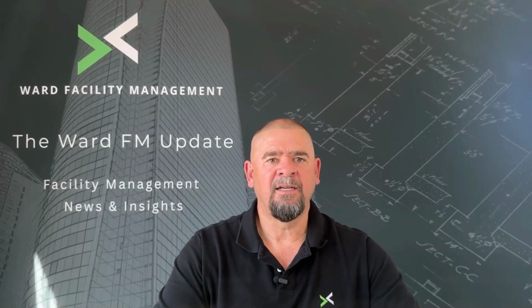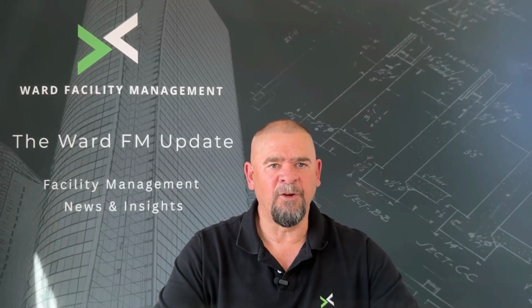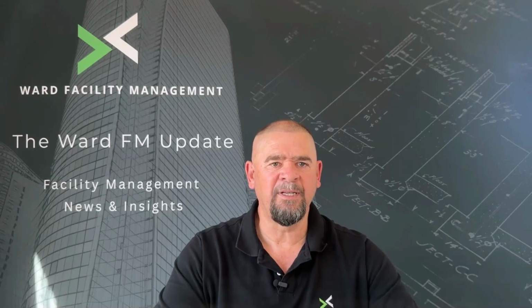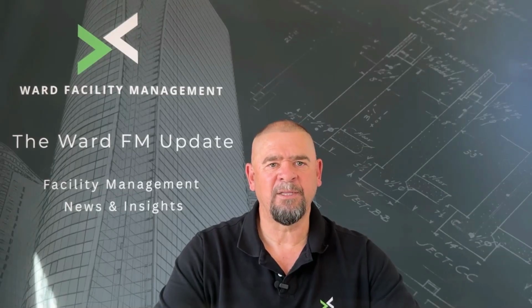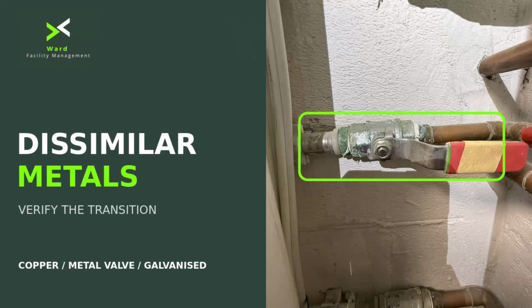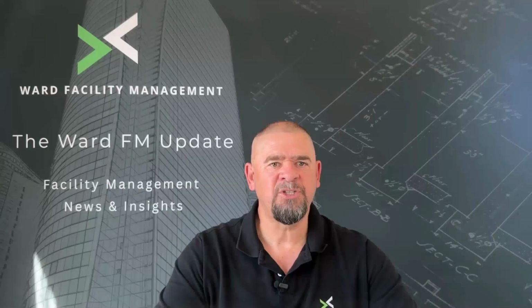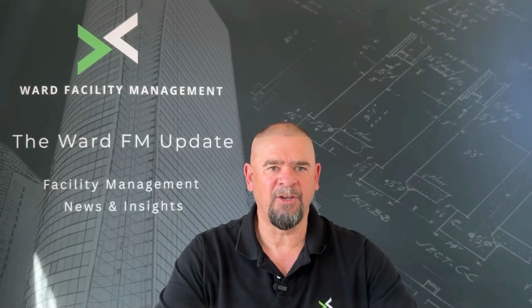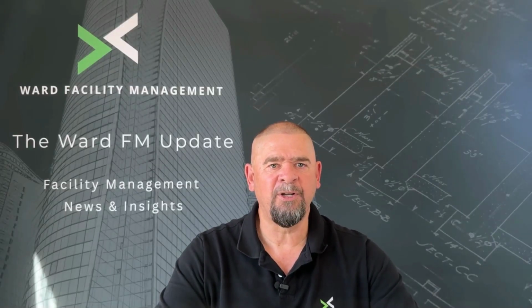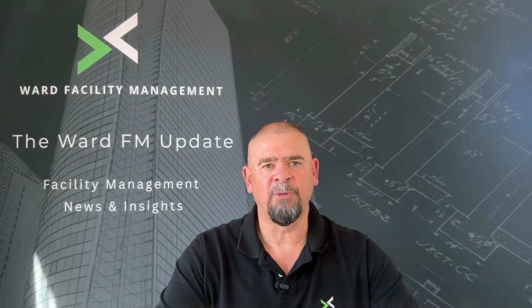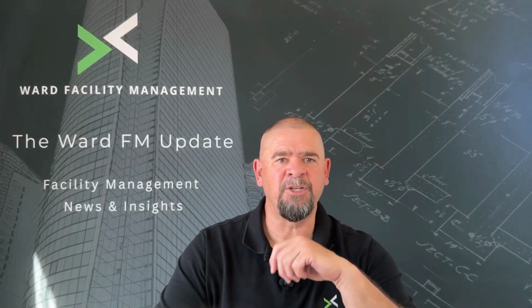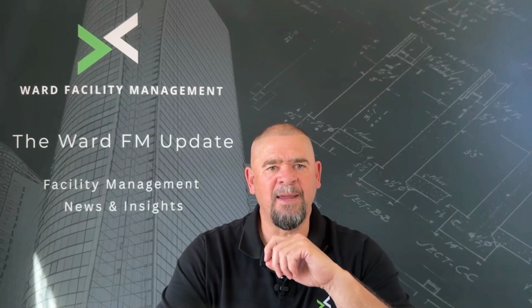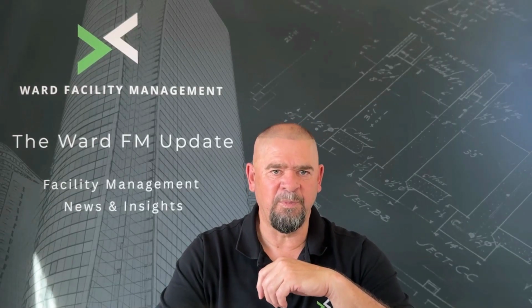The next area I considered was the connection between different metals. Copper and brass are commonly used together and are generally compatible. The more concerning transition is where copper or brass components connect to galvanized steel. When dissimilar metals are electrically connected and moisture is present, galvanic corrosion can occur. The galvanized or steel component will generally be the most vulnerable material. The risk increases when the protective galvanized coating is damaged at the threads, when the joint remains damp, or when the correct transition fitting has not been used.